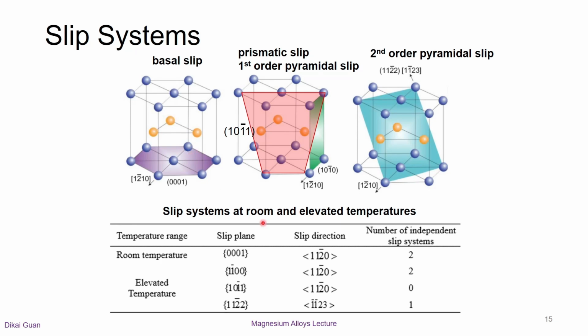As von Mises stated, at least 5 independent slip systems are required to plastically deform uniformly without failure. However, the strain on the basal plane produced by the third can be produced by a simple adding of the previous two. So only 2 independent slip systems are available. Because of inadequate slip systems at room temperature, deformation causes fracture or twinning. Thus, other non-basal slip systems or mechanical twinning need to be activated to facilitate plastic deformation.